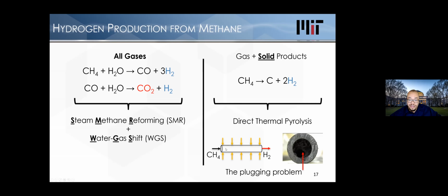So if you bring in methane, the simplest thing you can imagine is, okay, I'll put my methane in a tube, I'll heat it up from the outside, and what's gonna happen is you'll get your methane to decompose, hydrogen will come out the other end, but the carbon is gonna deposit on the walls. The problem with that is very quickly, it'll block the entire cross section of the reactor.